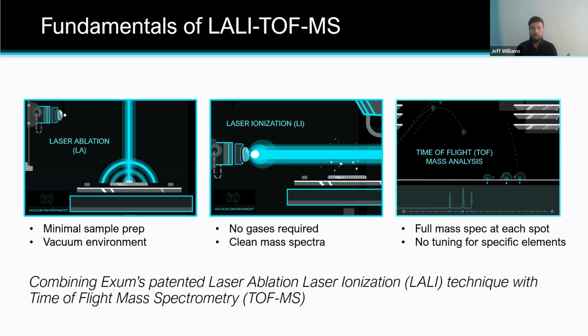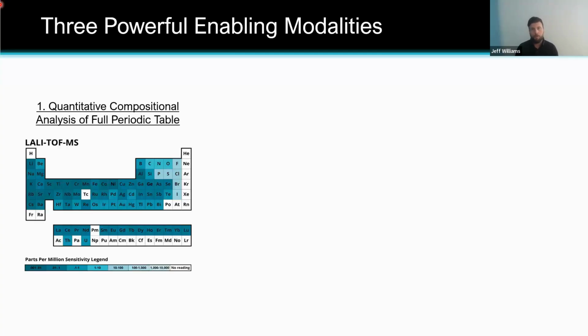And so what this enables us to do is, with this technique, we can do three major modalities. The first one is a quantitative workflow for most of the periodic table. So we like to say lithium to uranium, and we ignore the noble gases, right? We don't do those, but we do every other element. And critically, we do those light elements that are very difficult to do by other techniques. So that kind of top bar of the periodic table there. So we're very sensitive to lithium, and for a lot of the metal space, especially, but also relevant in batteries, we do a lot of carbon, nitrogen, oxygen work as well. And that's at every single laser shot that you get.